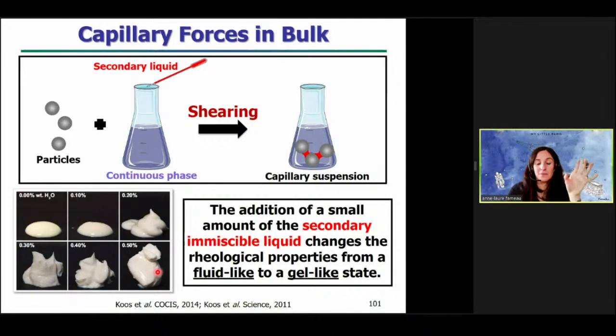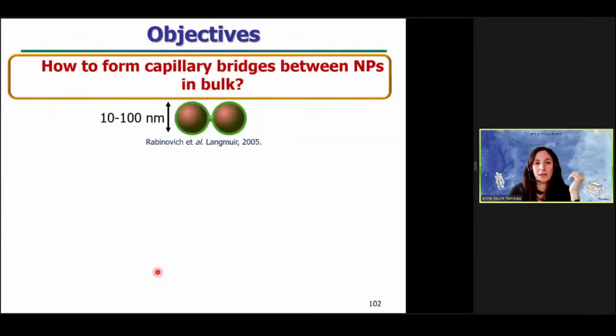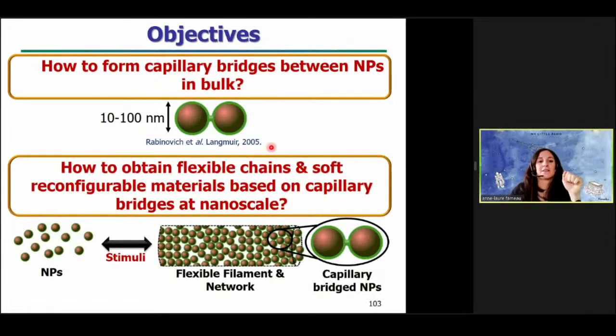But until our study, there was no proof that the capillary forces can work at nanoscale. It was always done just with micron-sized particles. So the first objective was to determine how to form capillary bridges between nanoparticles in bulk. From a theoretical point of view, it was possible, but from an experimental point of view, there was no proof until our study. And then the question was how to obtain flexible chains and soft reconfigurable materials based on these capillary bridges at the nanoscale. So the idea was to have some nanoparticles, to apply an external stimulus, to obtain flexible filaments and networks due to the formation of these capillary bridges between nanoparticles.